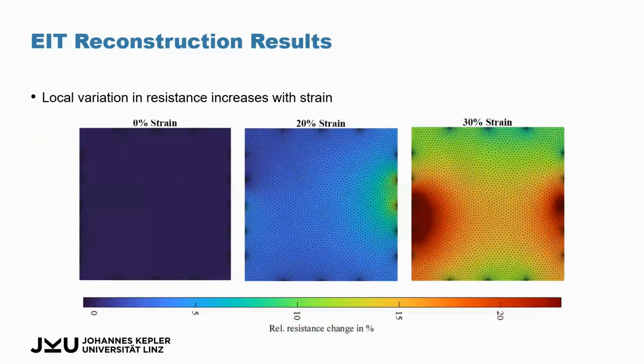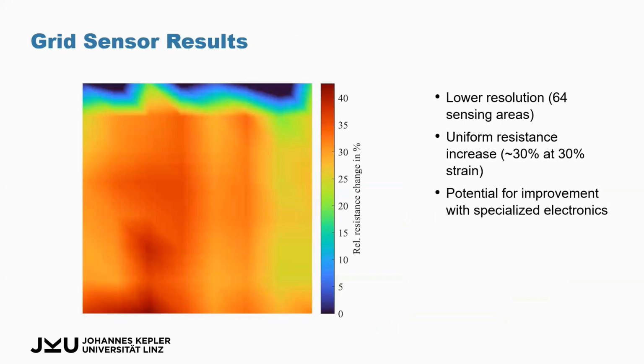Now for the EIT reconstruction results, you can see very nicely that with increasing strain, so this is 20%, we're starting to see a certain resistance change. And for 30%, we can see what we assumed, that due to the transversal contraction, the resistance change is not homogeneous. The grid-based sensor allows for a lower resolution, just because we have just an 8x8 grid. The resistance change is of a similar order of magnitude, but we don't see this transversal contraction. This is likely because we have crosstalk between the electrodes, and we're working on how to improve that and overcome that problem.